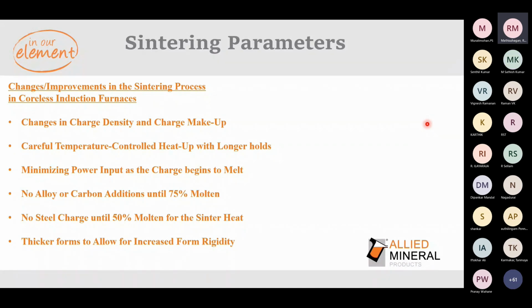Make sure you have a proper thickness for the former. Normally, we recommend 6 mm as a starting thickness, and when the furnace goes bigger, like 10 ton or 12 ton, we go up to 8 mm also. We don't recommend 3 mm because the refractory always has to be in compression. A 3 mm former has a high possibility of getting cut due to some kind of arcing, and if the former is cut, the refractory is not under compression, and in that area you can see a kind of spall. So we always recommend a proper thickness of the former.